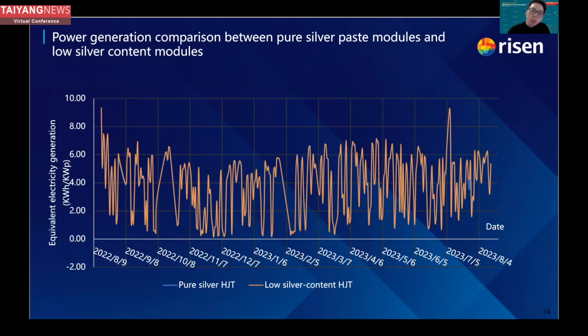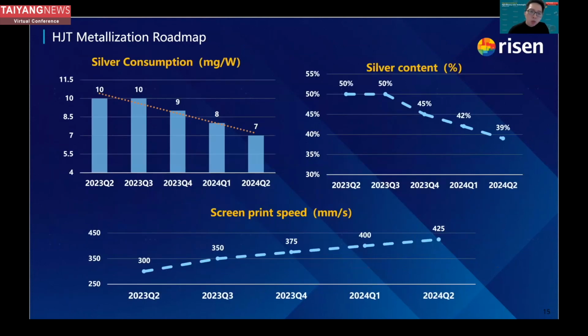And we also tested and compared a pure silver paste with our low silver paste heterojunction from October last year, and verified that the power generation between the pure silver silicon heterojunction cell and the low silver content heterojunction cell is basically the same, no big difference. And thus, we think this is the right way to reduce cost for heterojunction mass production while also maintaining the efficiency.